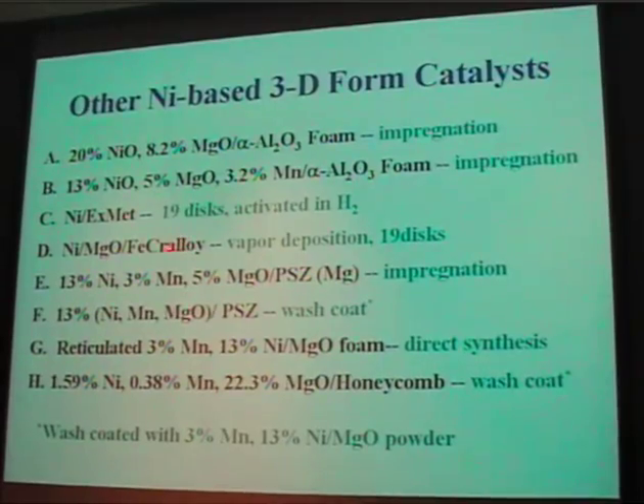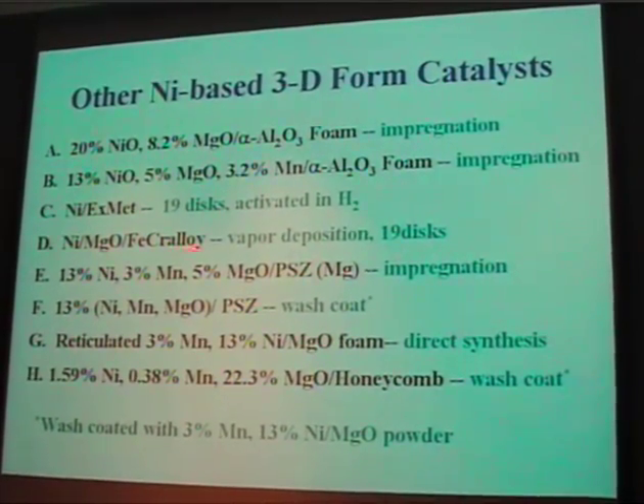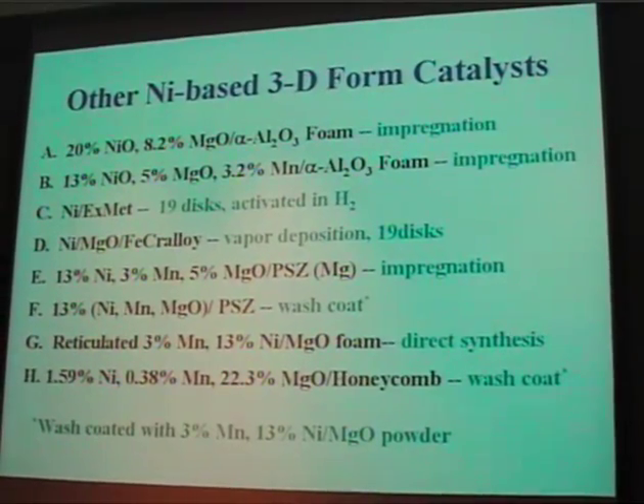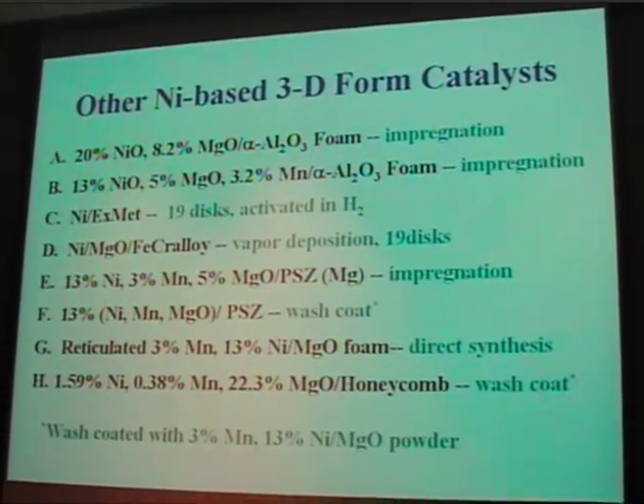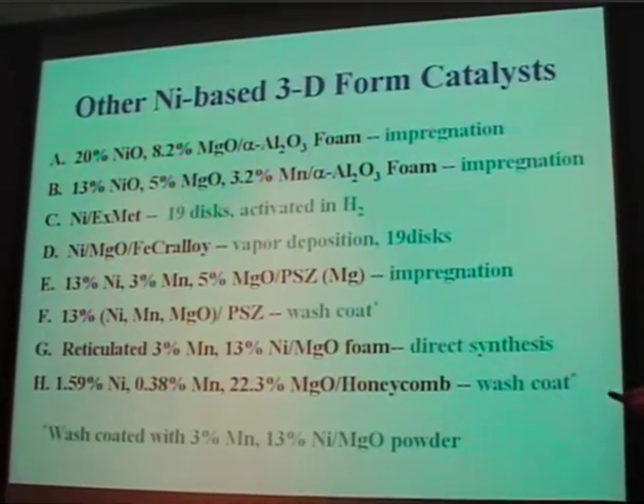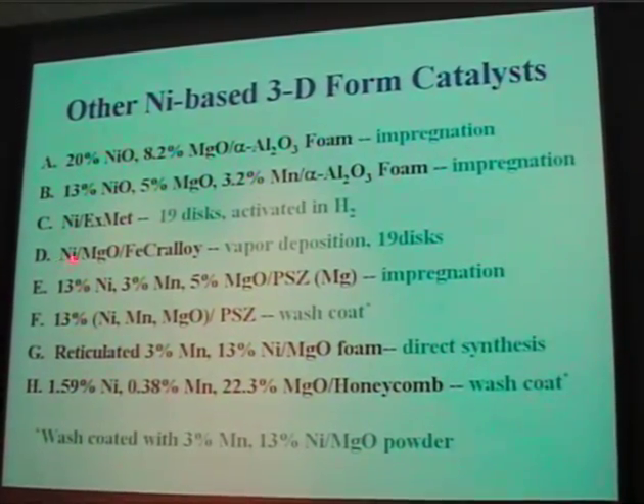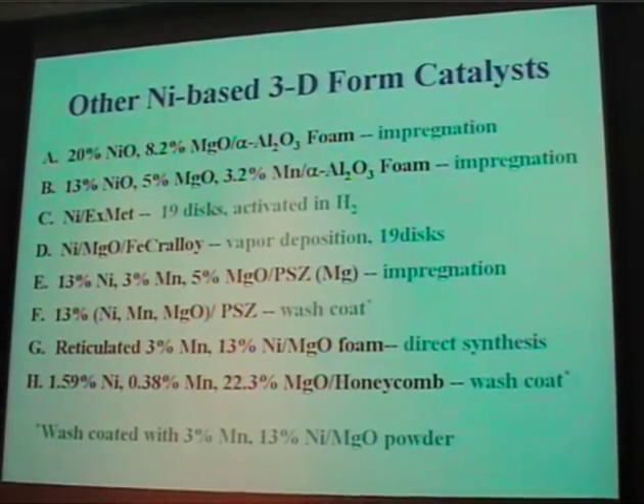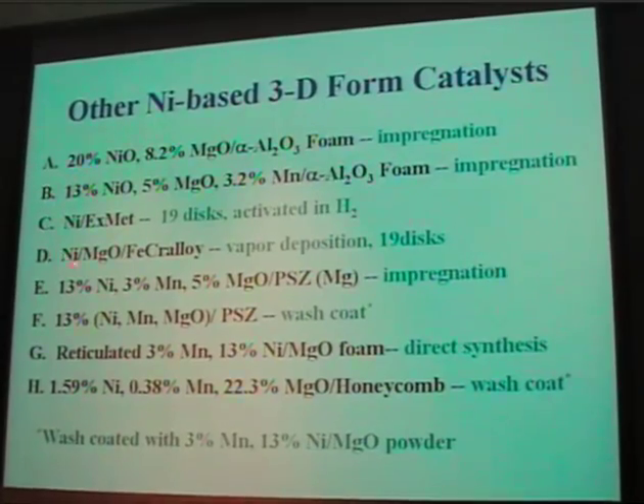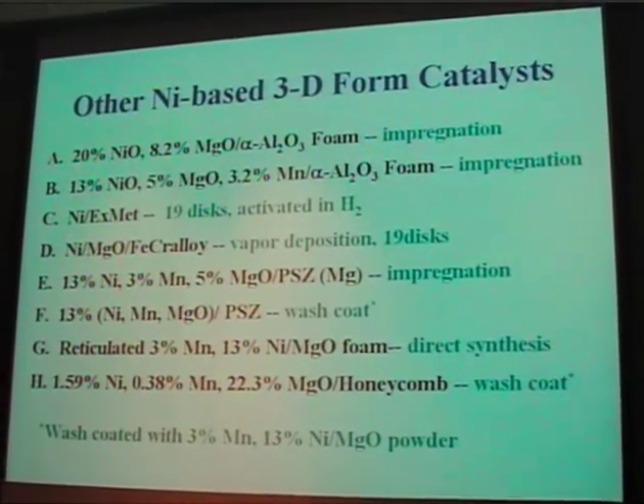Another approach was to take what's called iron chrome alloy. You can take that and calcine it to 1100 degrees C and form an aluminum oxide overlayer. And then on top of that, you can vapor deposit, we collaborated with the University of Delaware to do this work, to add on the nickel and the magnesium, oxidize it to the oxide. And again, we would have these as perforated structures and stack them. And we did some modeling to tell us what would be the best arrangement for perforation and rotation of each of the discs.